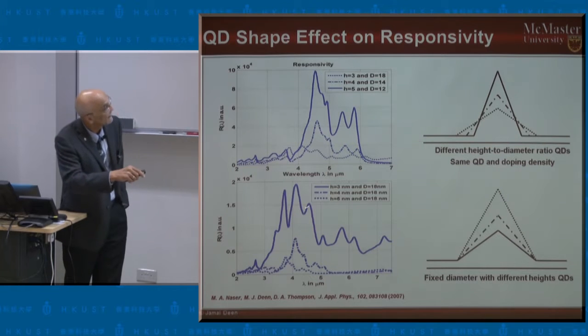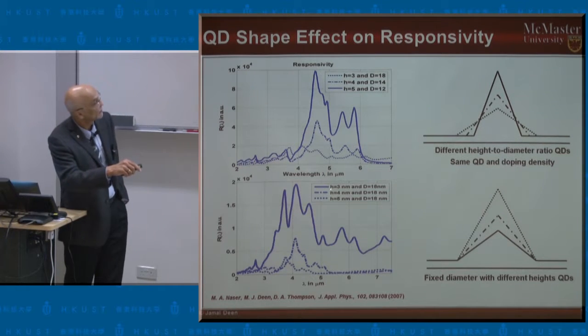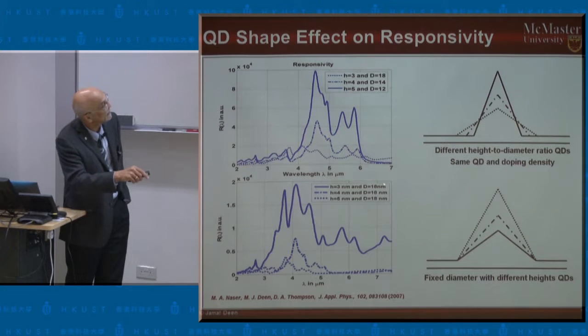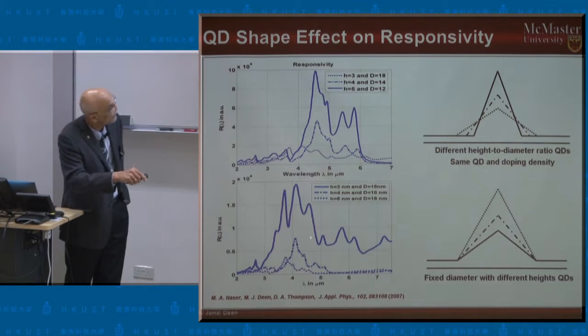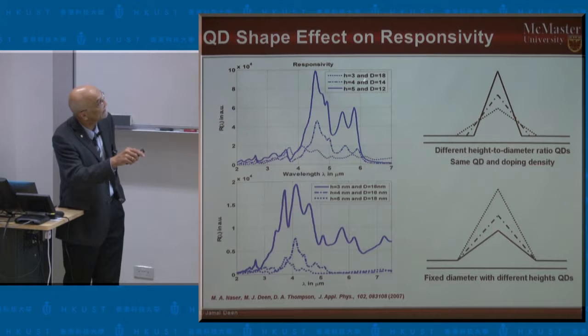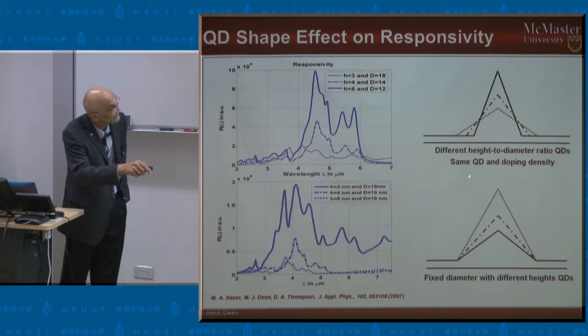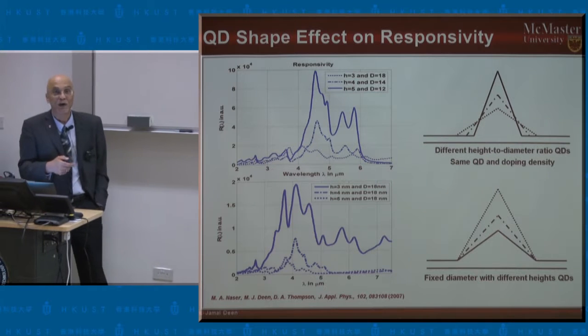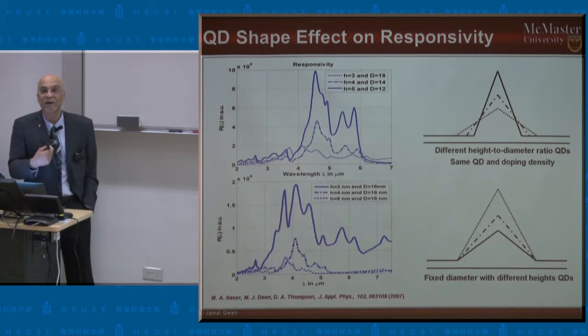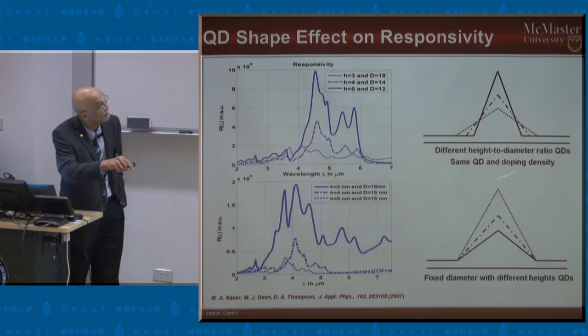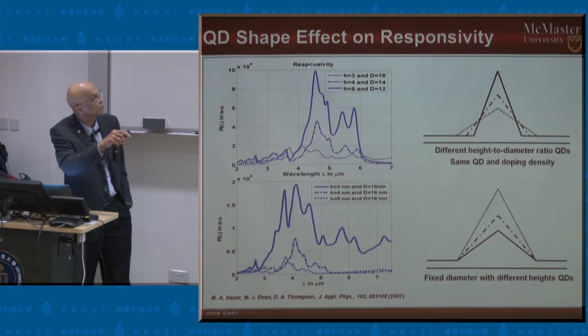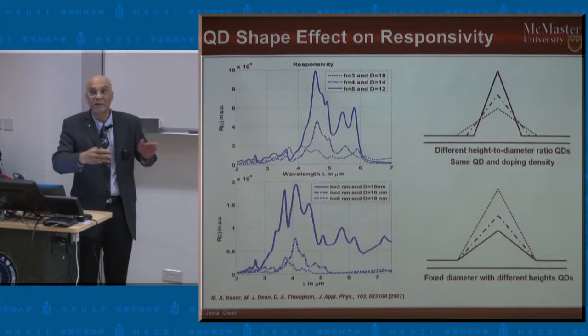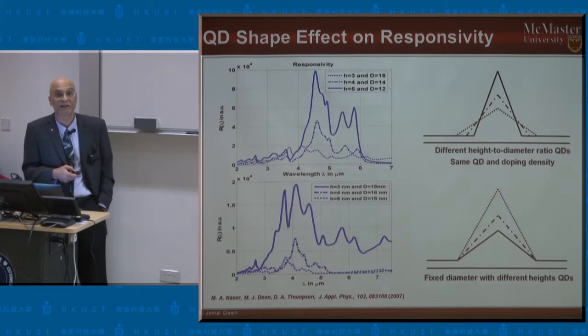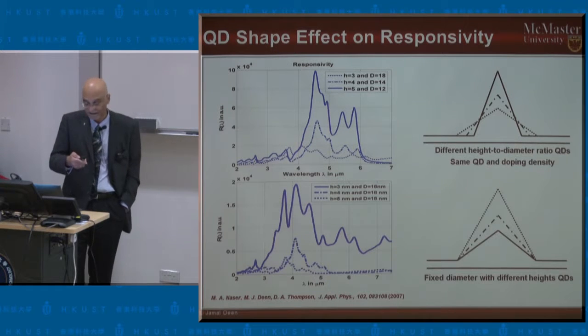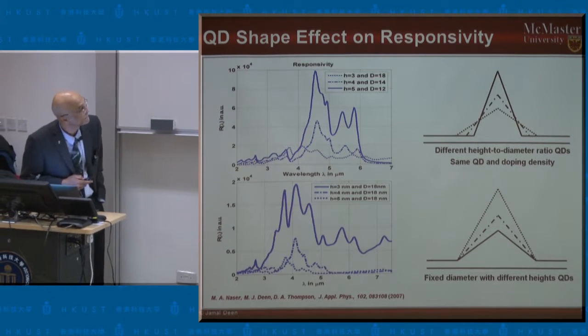And in this case, if we increase the height, so from 3 to 4 to 5, and we keep the dot diameter the same, so 18 nanometers, we can see that there's a decrease in the performance characteristic. In this case, there's an increase because we're increasing the diameter and the height to keep the density the same and the same number of quantum dots. So these are related to actually how we fabricate the device. So we can start fine-tuning the fabrication parameters so that we can improve the performance by playing with the height, by playing with the diameter, and by playing with the doping concentration. And in this way, we can design a device that has tailor-made characteristics.